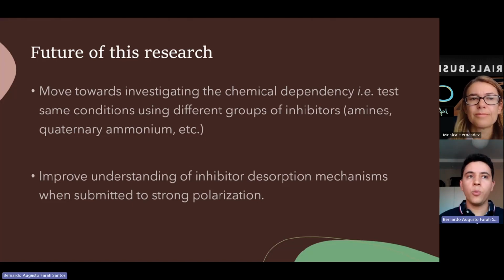There are several works, even using the potentiostatic technique or post electrochemical tests, that investigate this repassivation with stainless steel. But for carbon steel, whenever we use the corrosion inhibitor, we don't fully understand why the inhibitor may be dissolved by electrochemical forces and then readsorbed on the surface. Let's say if you make a cycle, polarizing and depolarizing the surface. So that would be interesting in terms of understanding